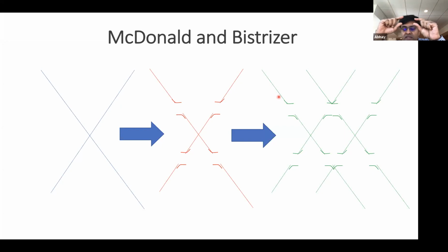If you have a 2-state system and electrons are hopping between the 2 states, then in general, you'll produce a bonding and anti-bonding orbital. And so when MacDonald and Bistritzer did this calculation properly, this is the band structure coming from one of these 2 graphenes, and this is the band structure coming from the other graphene. And they're not sitting at the exact same point because they're twisted with a small angle relative to each other. And then when you properly account for the fact that hopping can exist between the 2 layers, you find that exactly at this point, you are going to produce bonding and anti-bonding states.